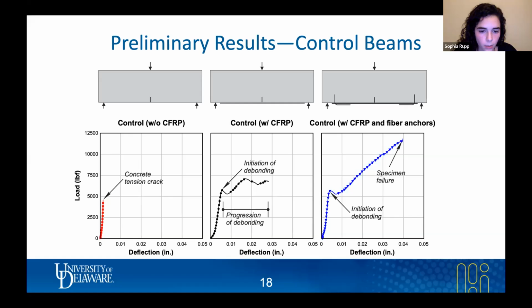And once that initiation of debonding starts to happen, you see a slight increase in stiffness and a slight increase in load. However, the progression of debonding will continue, and those tensile cracks in the concrete will start to form once it really starts to debond, and that will lead to failure eventually.